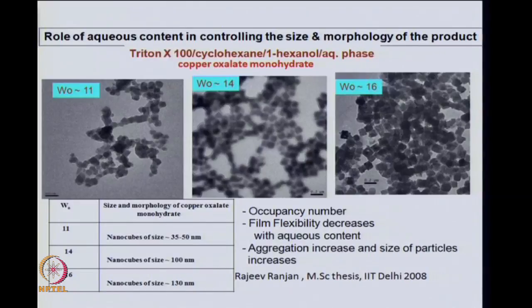Now, you can further see this in the case of another surfactant, other than CTAB. If you use another surfactant like Triton X-100 and you vary the W0 parameter from 11, 14 to 16, in this case what happens, you are changing the W0 parameter, the size of the particle is increasing because you have more water, more crystallization, the reverse micelles are larger in size and the size of the particle increases. So, this is the case where you have taken a neutral surfactant, where you get uniform, cube like particles and not rod like particles.